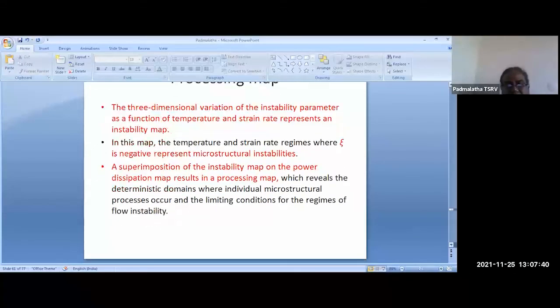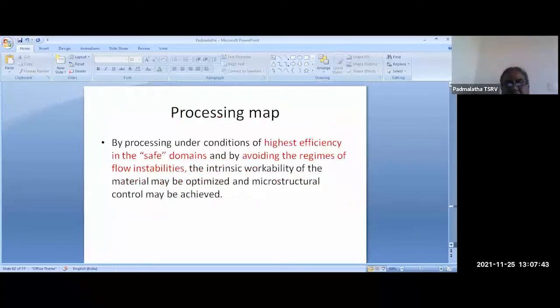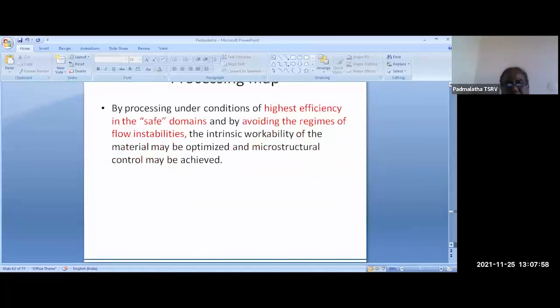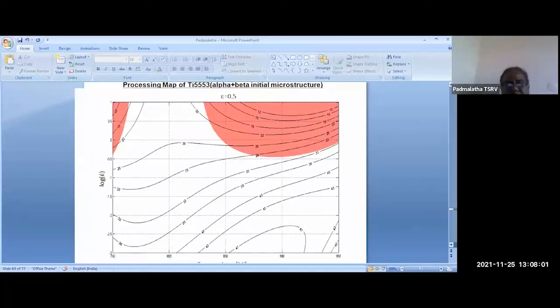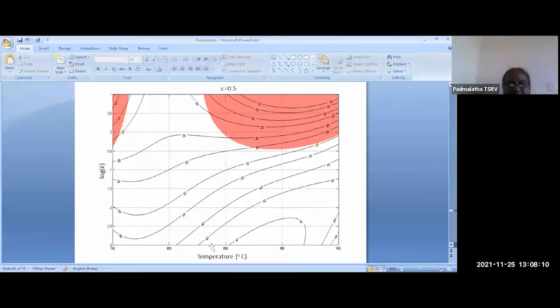So one case study we'll see here. I told you that whenever the efficiency is more, those are the safe domains, and whenever the xi factor is negative, that is an unstable domain for us. So these are the processing maps. I will take one case study. This is a processing map we have generated for our material titanium 5553 with alpha plus beta initial microstructure. Here we can see that the x-axis is temperature and the y-axis is the strain rate.